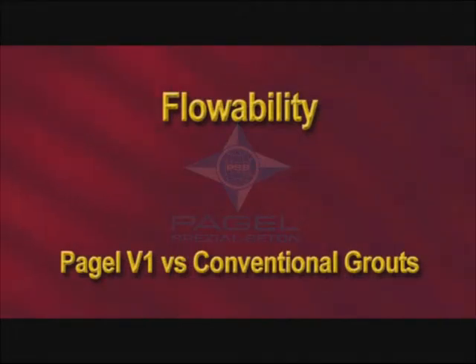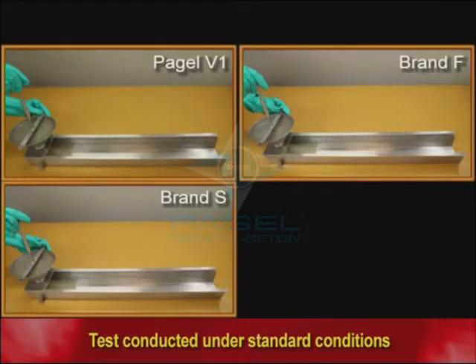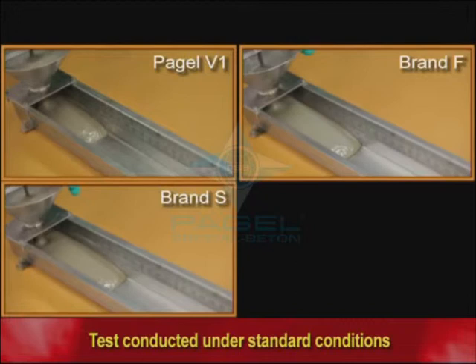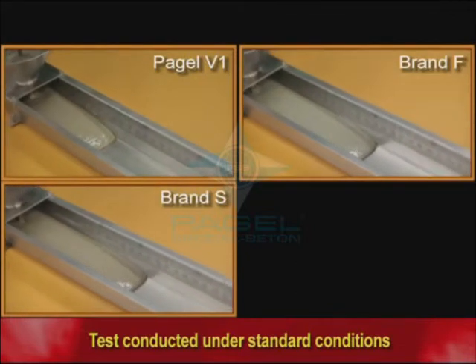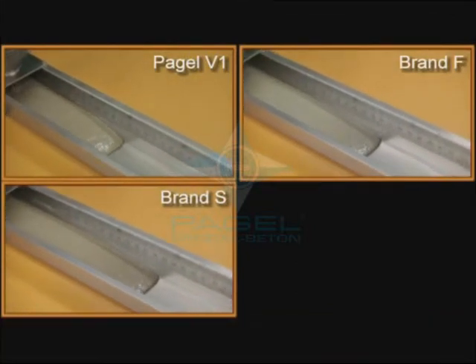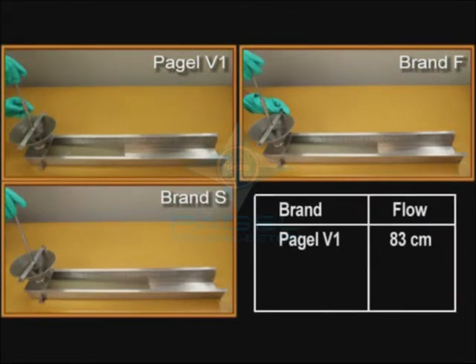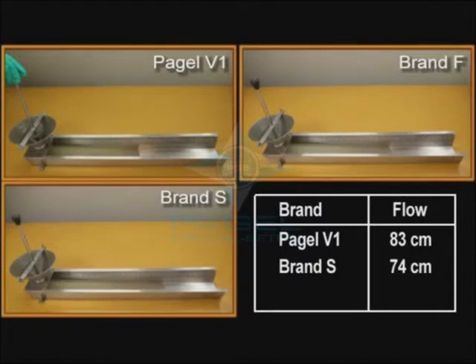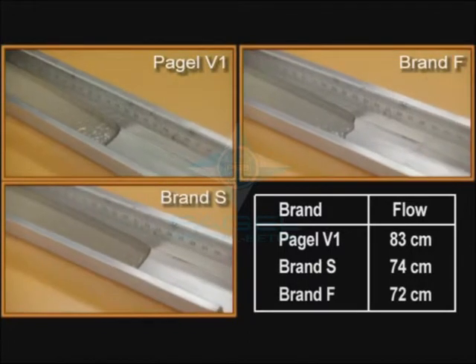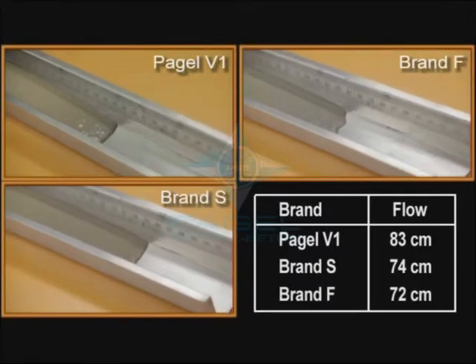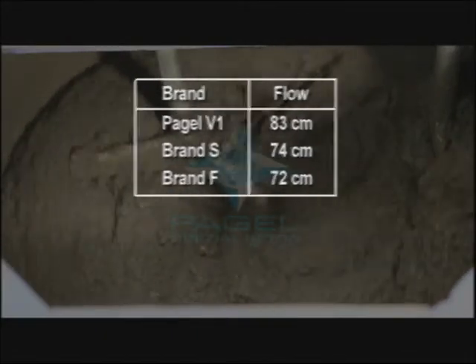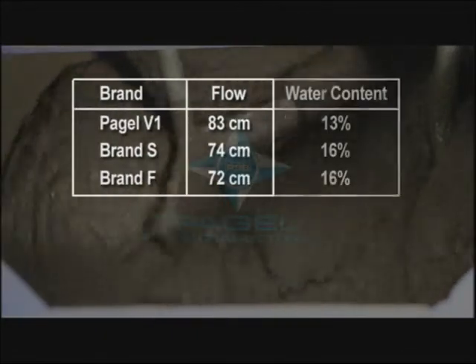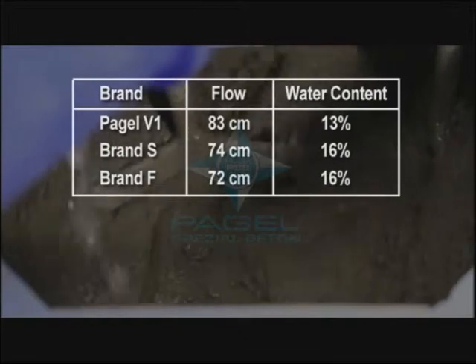Flowability is one of the most important properties for a grout. In a flow channel test, the Pagel V1 grout flows most smoothly and cohesively like lava, reaching 83 centimeters compared to 74 centimeters for Brand S and only 72 centimeters for Brand F. And Pagel V1 achieves this with a lower water-to-powder ratio.